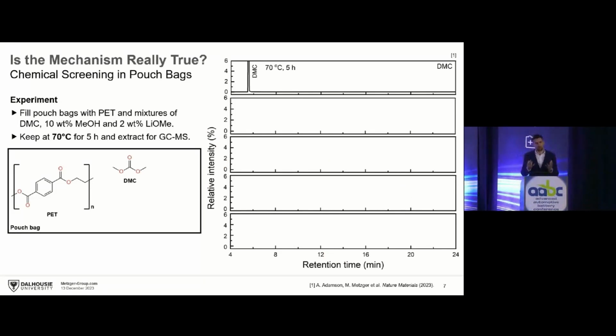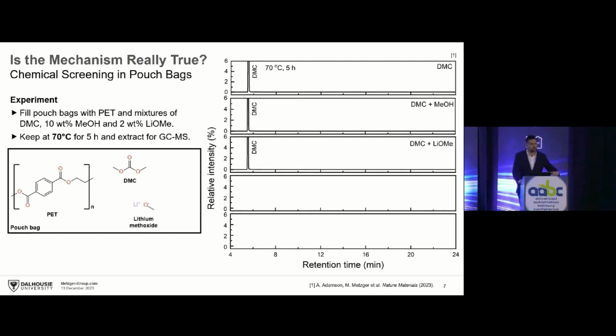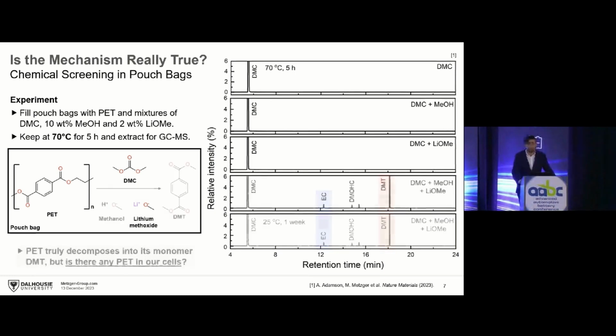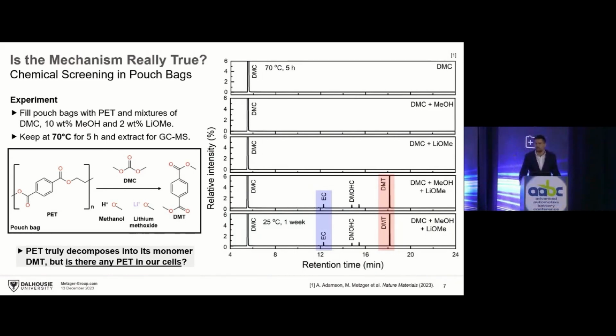So what we do is we form a little pouch pocket, we call it. We take our pouch foil material, form a bag with it, and just add a PET film and DMC as the solvent. And then we heat it to 70 degrees Celsius for 5 hours and do gas chromatography on the liquid solution inside. And if we do that, we don't find any reaction products. If we add methanol, also no reaction products. So we replace methanol with lithium methoxide, still no reaction happens. But if you add all three ingredients, like in this reaction cascade that I have shown you, then indeed you form ethylene carbonate and the DMT shuttle molecule. And you don't even need the elevated temperature if you have those ingredients, even at room temperature. This reaction proceeds.